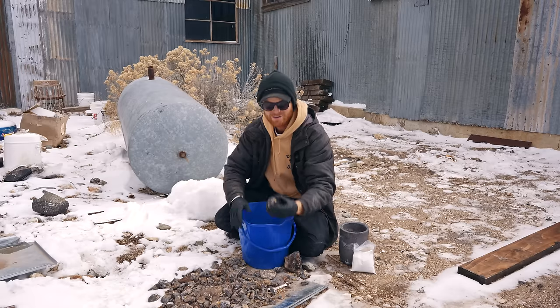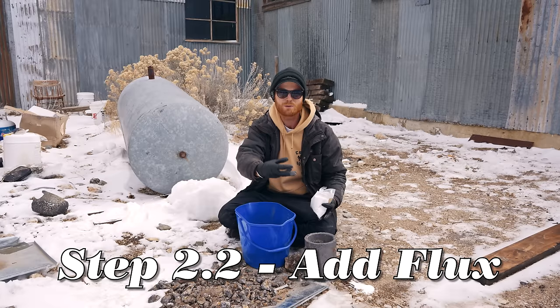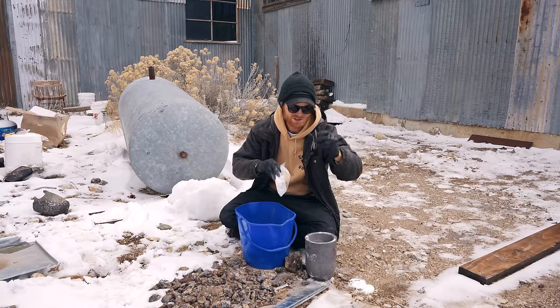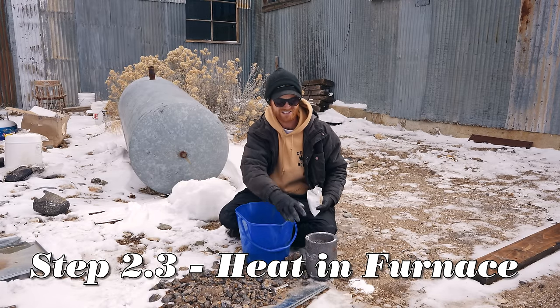So we got our galena out of the mine, crushed this up, and we're gonna add in what's called flux. The flux is gonna pull out everything that isn't lead and silver. In this case, we're using soda ash. We're gonna add some iron into the mix too. In this case, I'm just using some old nails. Throw that in, take it over to the furnace, and heat this up to about